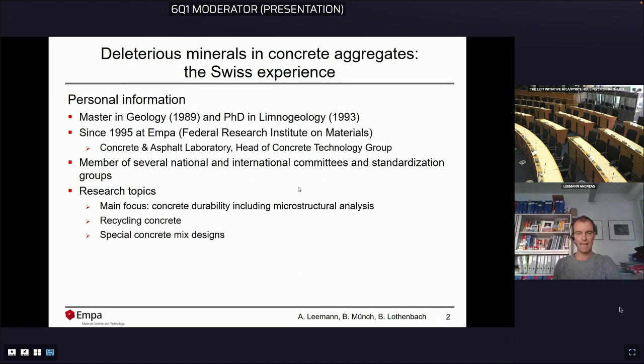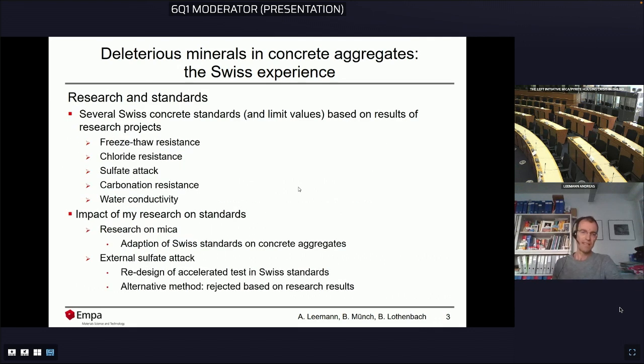Next, please. So, dynamics of research and standards. Several Swiss concrete standards and their limit values are based on results of research projects. This goes from freeze-thaw resistance to chloride resistance, sulfate attack, carbonation resistance, and water conductivity. The impact my research had on standards was the following. The research on mica resulted in adaptation of the Swiss standards on concrete aggregates. My work on external sulfate attack led to the redesign of the accelerated test in the Swiss standards, and an alternative method to test sulfate attack was rejected based on a project I did. So you see, research can really influence standards.